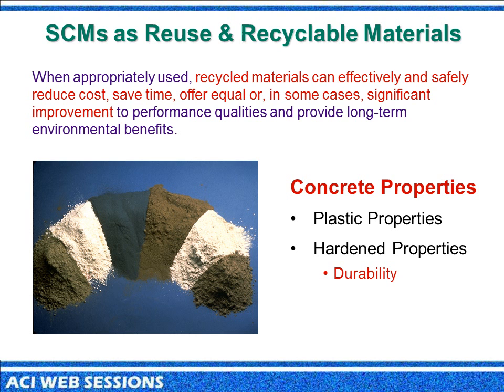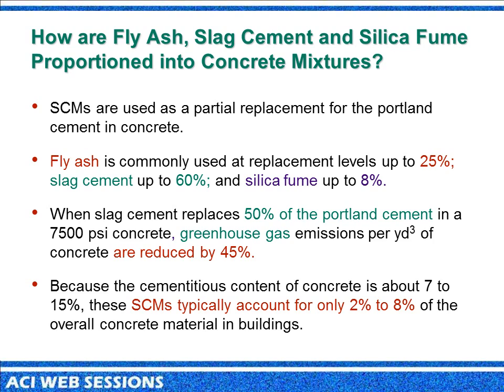What's also nice is that using SCMs allows us to use a recyclable material, which is one of the parts that we look at in sustainable construction. We also benefit by using slag cement and silica fume in the same mix, as we see some balancing of the concrete plastic properties. But more so, we see a better kick in the hardened concrete properties, particularly durability and perhaps ASR. More importantly, when we look at substitution with supplemental cementitious materials, we can really see that there is the ability to reduce greenhouse gas levels.